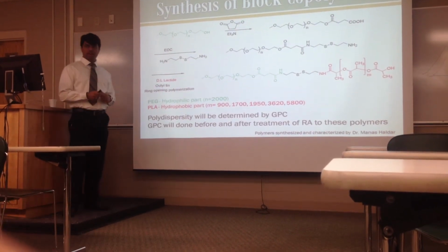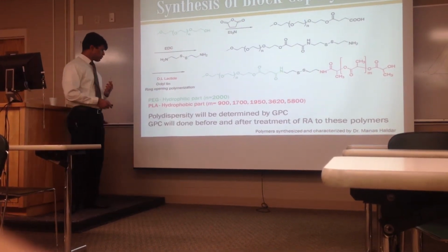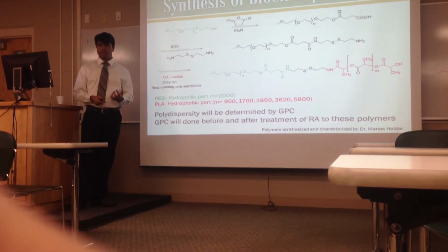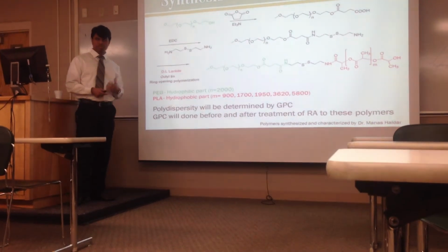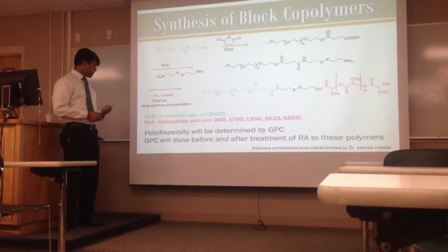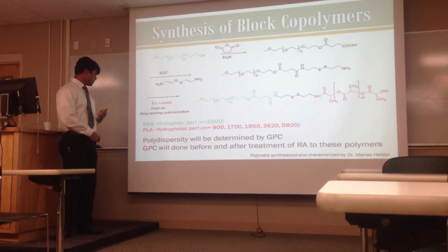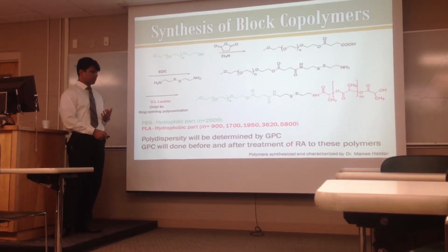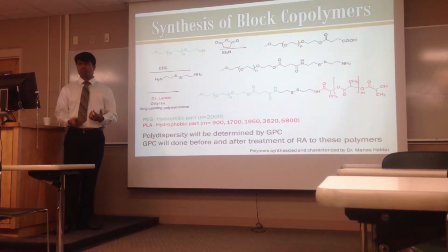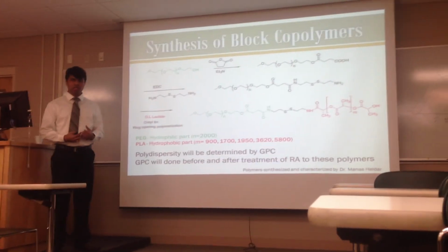We have not yet characterized these polymers, but we'll be characterizing them using gel permeation chromatography to check the polydispersity of these polymers. And we'll also do GPC before and after treatment with the reducing agent to check whether these polymers are getting cleaved by the reducing agent or not.